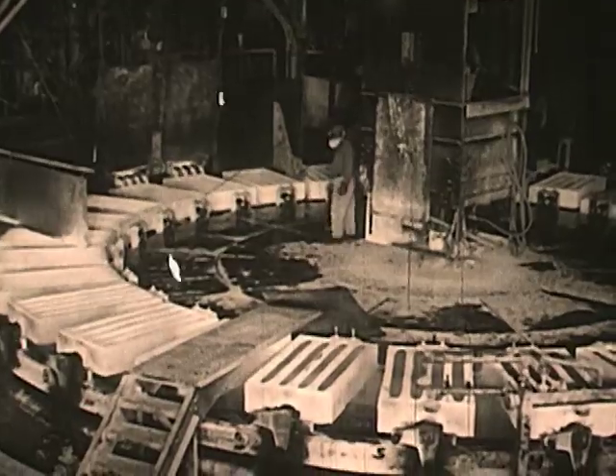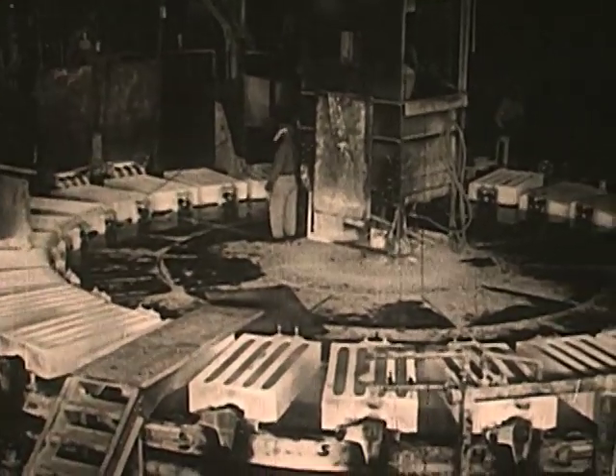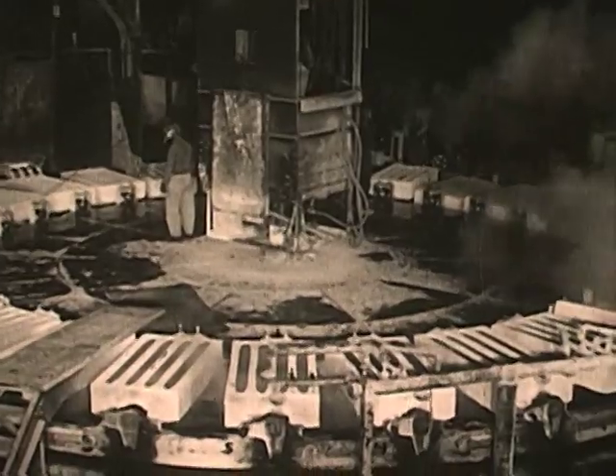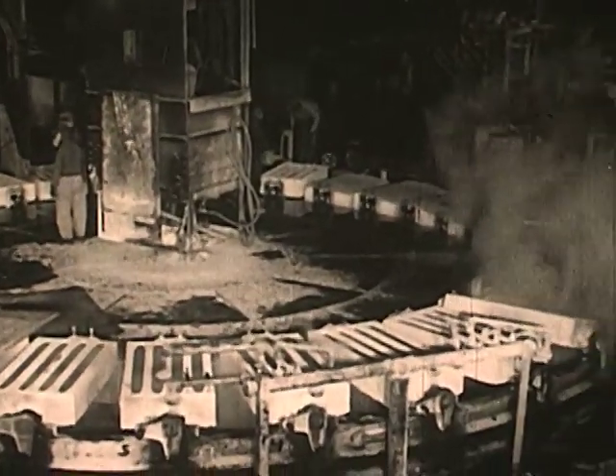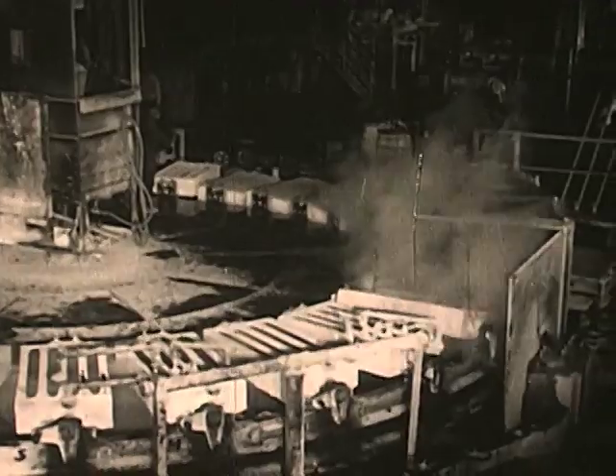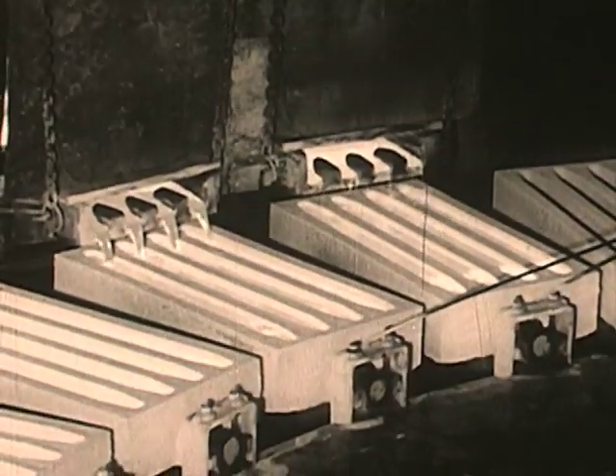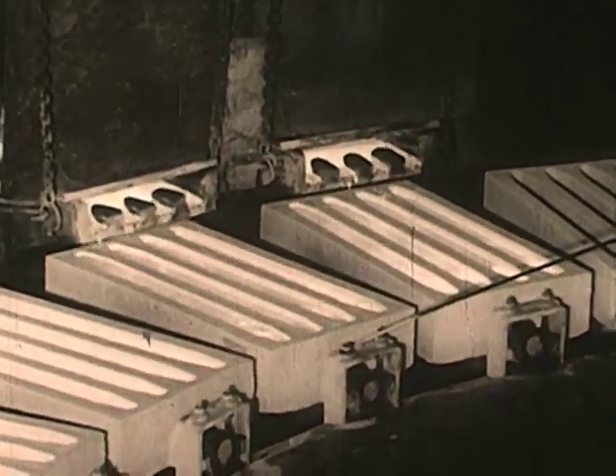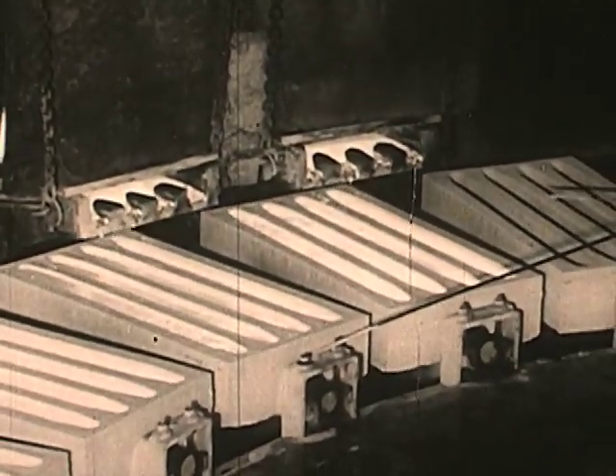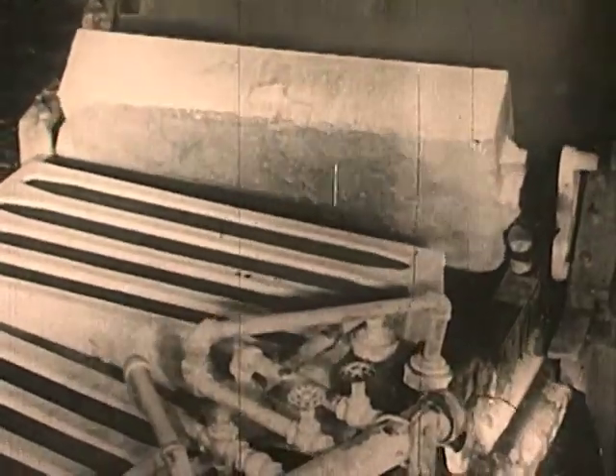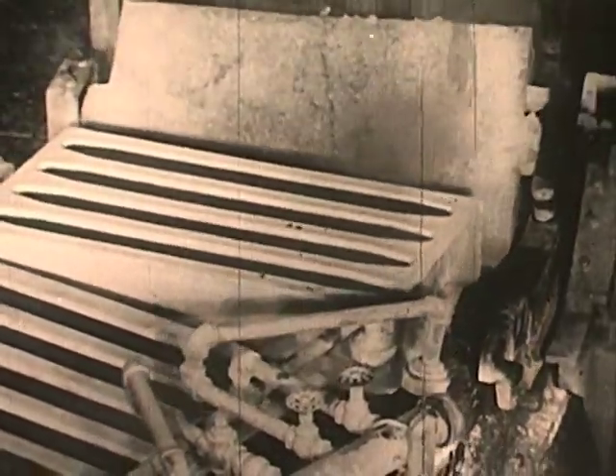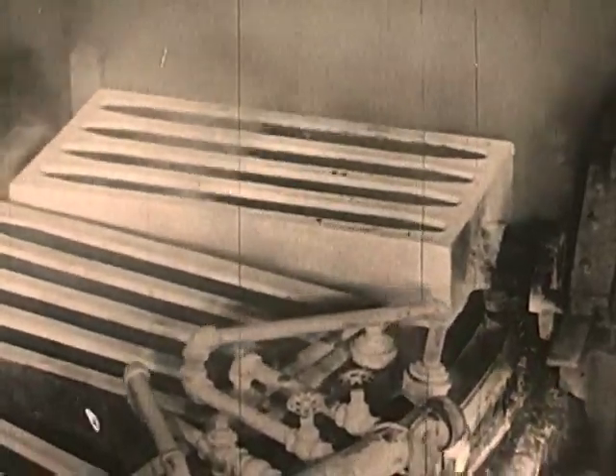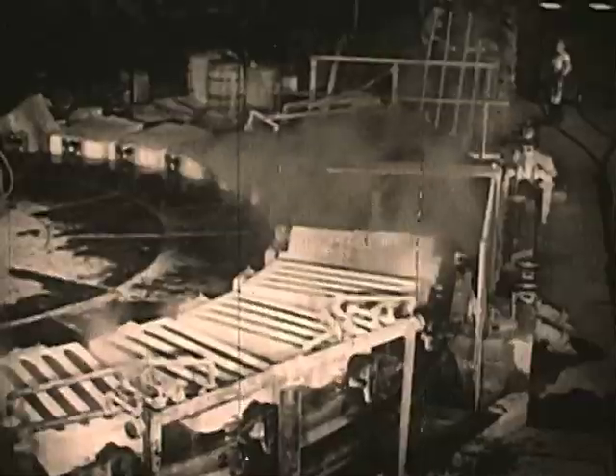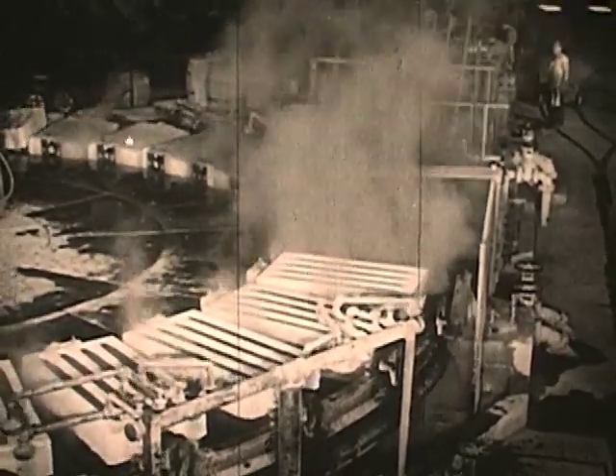Here a casting wheel 40 feet in diameter casts 200,000 pounds of refined copper into bars every hour. When the furnace is tapped, the molten metal is delivered successively to the 30 moles on this wheel. The moles themselves are made of copper, but are coated with bone ash to prevent the hot metal from sticking. Moles of different shapes are used to produce different commercial shapes of bar. The wheel revolves as the moles are filled, and the newly cast bars are dumped into a water bath for quenching.